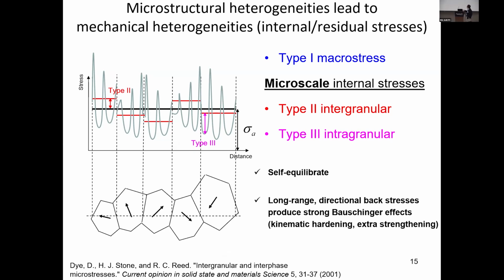For a polycrystal sample, if you measure or compute the stress across the grains, the black solid line represents the applied constant stress or the load, while across those grains, we have the green average stress represented by those red segments. They deviate from this applied stress. Those deviations are called type 2 intergranular internal stresses. While within each individual grain, because of, for example, the chemical cell and dislocation cell structures, we also can have very strong stress fluctuations across the cells. Those are deviations from the green-level averages, and these are called type 3 intragranular internal stresses. As you can imagine, as you bring in more heterogeneous microstructures, you would have more fluctuations, and they can significantly impact the mechanical behavior of materials.